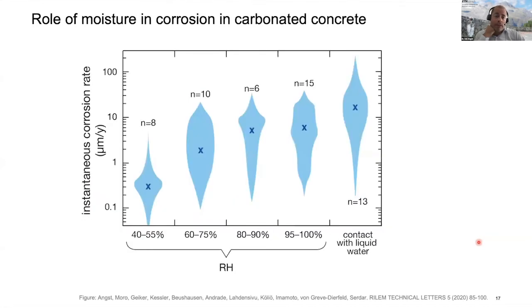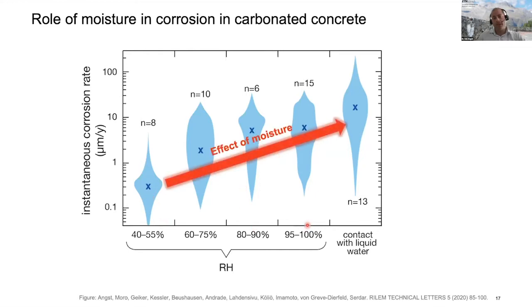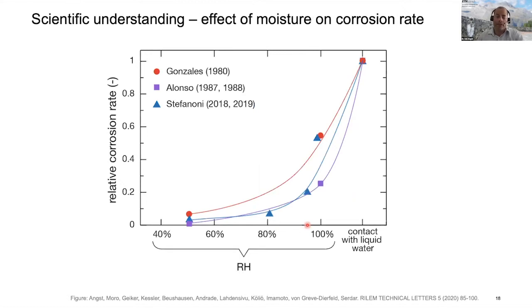And it is also well demonstrated in the literature that the instantaneous corrosion rate for steel in carbonated concrete increases when we increase the moisture condition. Now, in fact, there is a dramatic increase in instantaneous corrosion rate. If we go from something of around 80% relative humidity to a condition where the concrete is in contact with liquid water, we increase the instantaneous corrosion rate by a factor of 5 to 10.